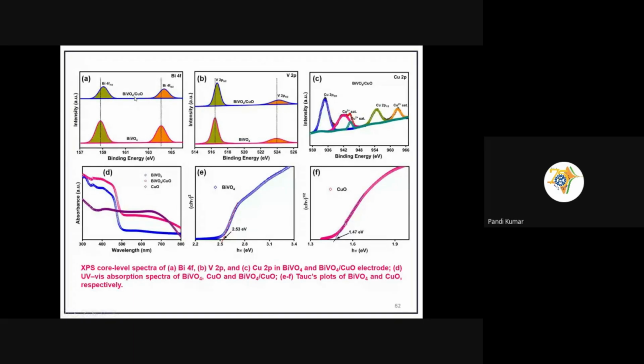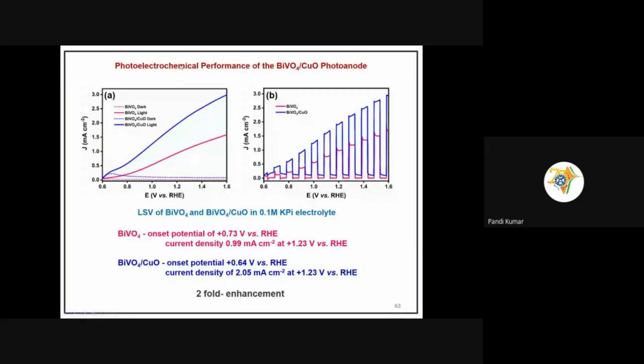So after forming the heterojunction, the shift in the binding energy indicates surface charge transfer between these two, leading to the formation of the heterojunction. Then the band gap value and optical studies we have also carried out by adopting the Tauc plot method. Here after forming the heterojunction, visible light absorption is enhanced for this bismuth vanadate. Then we carried out the photoelectrochemical water splitting experiment. In the dark condition, it shows a poor response, but upon illumination, it shows a higher photocurrent response.